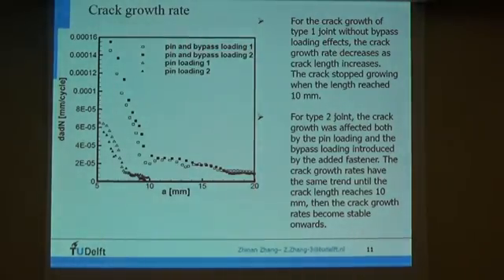Previous studies have found that the fatigue damage tolerance of metal laminates can be divided into two main mechanisms. First of all is the crack growth rate. So let's talk about this one first. We can see from this picture, the upper two lines are the data from the pin and bypass loading test. The lower two lines are from only the pin loading test.